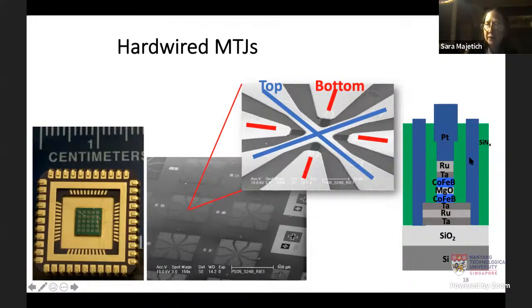We can go in through the bottom electrode. Here we've got platinum coming down, connecting to the tantalum ruthenium layer underneath the tunnel junction. And then at the top electrode, we've got platinum coming down here. And so underneath each one of these flowers is a single MTJ.